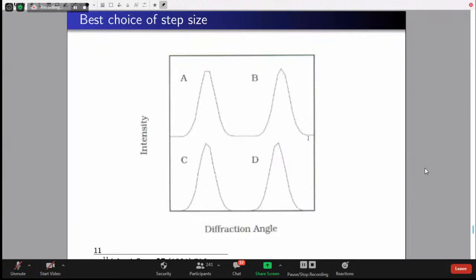It depends, sir. The best case scenario is assuming that you have a fully crystalline sample. Then 0.02 will be a good step size. If it is not crystalline, and a large amount of amorphous nature is still there, then we should go for 0.05 or even 0.1, because the smaller the step, the more we are contributing to the noise rather than to the peak.